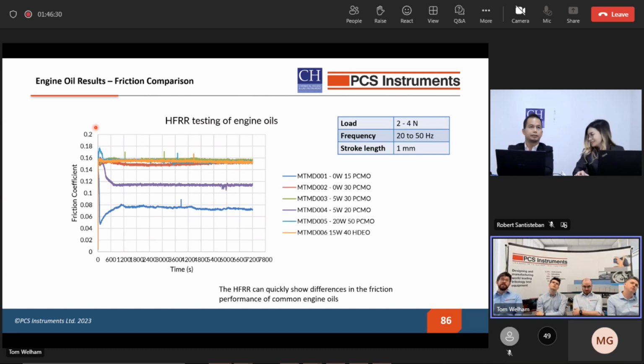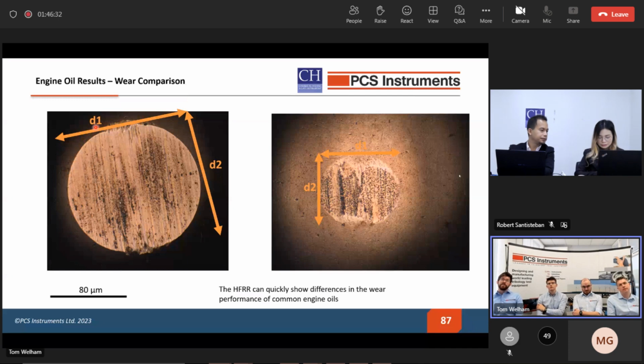So post-test, we can look at the level of wear as well. So the HFR specimen holder can be taken off and taken to a microscope or a white light interferometer, and we can measure the diameter of the wear scar and compare that with different oil formulations, which is very useful. And here we have two images. So we can look at the two perpendicular diameters, D1 and D2, which would define the diameter of this contact. And this could be averaged to get the mean diameter of the wear scar. And this is a really good quantity to quantify the level of wear which occurred throughout the test.